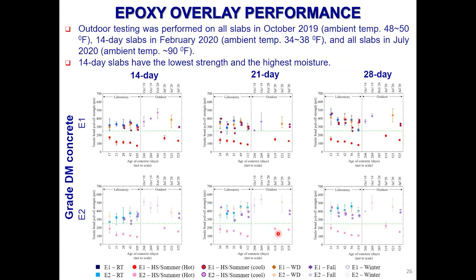So we can say, with mature concrete with low moisture content, we see the same performance. Once it cools down, yes, it's going to revert back to gain the required strength. And also when we test it under freezing conditions, we see higher strength. So the biggest factor is the temperature.